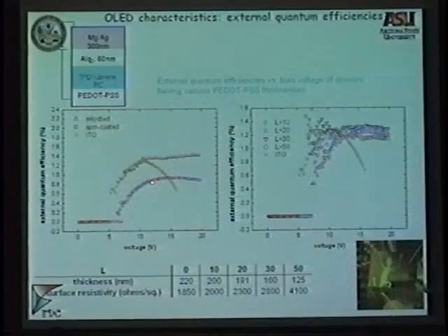Just compare the three quantum efficiency performances. You could see that indium tin oxide, since it allows higher currents at high voltages, therefore allows much higher Joule heating, which degrades the device pretty rapidly. Therefore, if you compare the three performances, inkjet comes out on top. It has very flat performance, even up to 20 volts, in quantum efficiency, and that's what you need in your device.